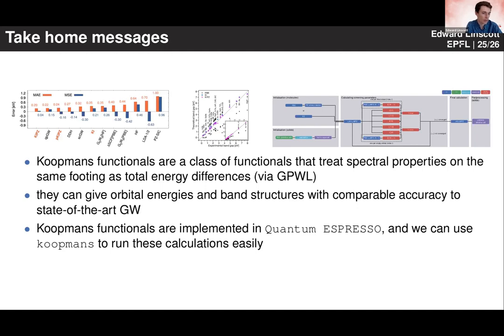So exactly, for the moment, we've stayed away from systems that are canonically strongly correlated. What we try to cure is this piecewise linearity, and that is part of the picture for these strong correlation materials, but it's not the total picture. So while we'd definitely improve results, I don't think it would be perfect. In contrast, for your typical prototypical semiconductors and insulators, we don't need to worry about these multi-configurational effects, and so we can rely on our Koopmans results a lot better.